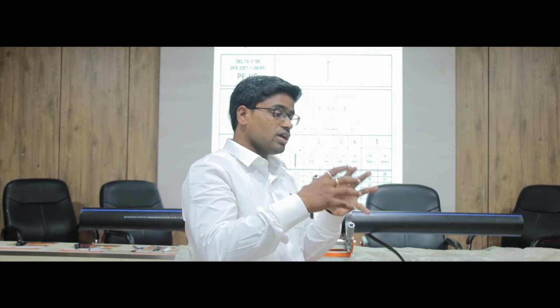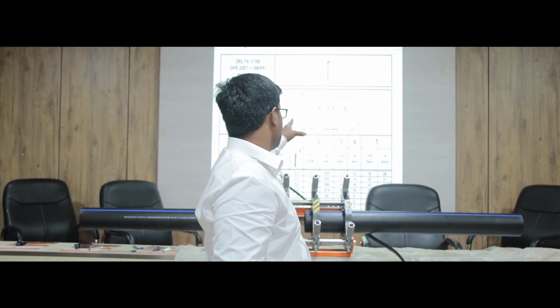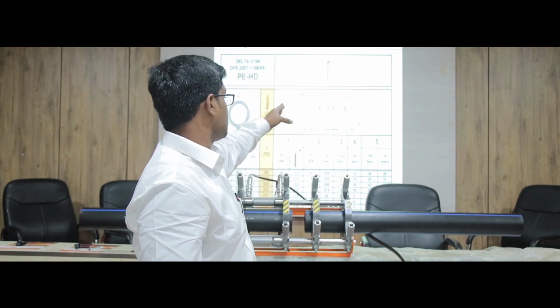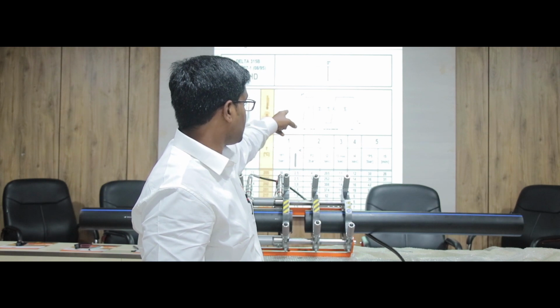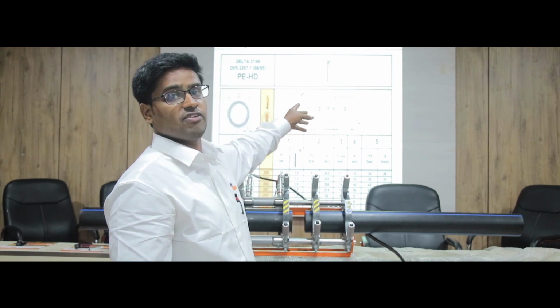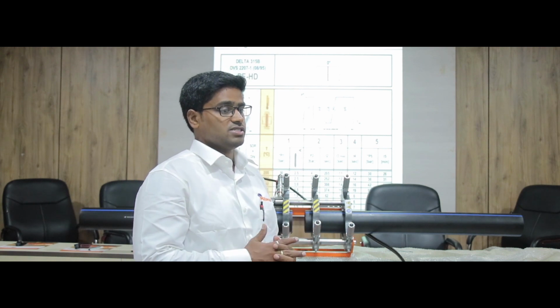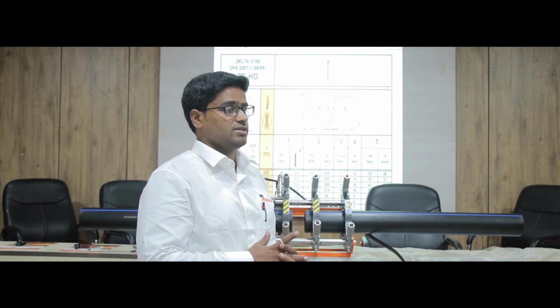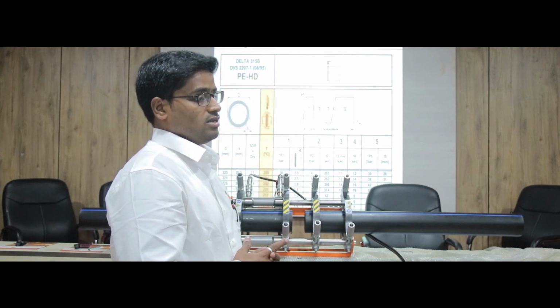When the fusion has already occurred, then why are you again increasing the pressure? No, cooling has to be done under pressure. That is the actual. Sir, out of these 5 phases, the 5th phase is the actual welding phase. During that phase, welding will happen. Only the hot plate is not there, but the welding will occur at that time.